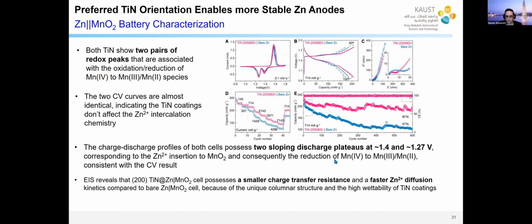Incidentally, one of the things we also think is that this battery is not only for grid scale storage. One potential application is to replace the lead acid battery in conventional cars. That lead acid battery has two features: one, it runs at very high rates, but also it doesn't last very long in the number of cycles. So if we could get the zinc-ion battery to last 600 cycles at a high rate, we could start thinking about replacing it, because we are using much more benign materials, no lead and low sulfuric acid.